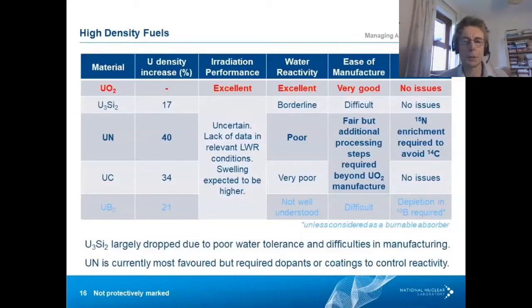Looking at the other higher density fuels, a large number have been examined over the years, and some are still under consideration for fast reactor applications. They are, however, in general, much more reactive than uranium dioxide. The four listed here have all been looked at to some extent during the recent years, and both the carbides and the silicides have fallen by the wayside as a result of their poor reactivity with water. The main contenders still under development at the moment are nitride fuels, where continued work on doping and modifying the fuel to enhance its resistivity to water exposure are still underway.